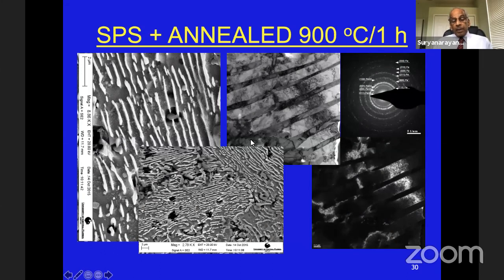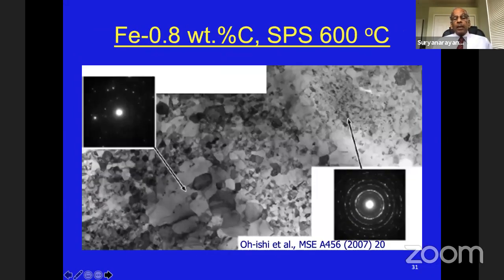These are the TEM, transmission electron micrographs. These are the scanning electron micrographs. You can see the ferrite, cementite, ferrite, cementite, alternate lamellae, and then you have the diffraction pattern. And if you look at the dark field picture, the white portions, the highlighted portions, represent the ferrite portion, because this is taken from one of the ferrite reflections. So you can produce these things very uniformly by our technique. But this is a micrograph from one of the previous workers, wherein you can see large grains, small grains, grains of only ferrite.